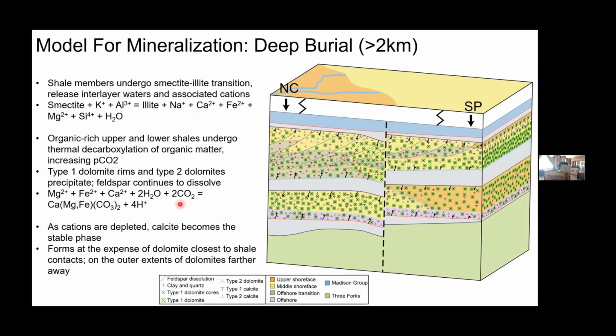Then lastly, those cations are depleted. As we use more of that magnesium and more of that iron to precipitate more and more ferroan dolomite, eventually calcite became a stable phase and filled in the pores outside of the dolomites. In some cases, as we're closer to the organic rich upper and lower shales, calcite formed at the expense of dolomite, whether that's due to an increase in the partial pressure of CO2 there, making calcite a stable phase, or there was just a lot more calcium there for whatever reason, I'm not sure. But we definitely see an enrichment of that phase at the contact of the upper and lower shales.